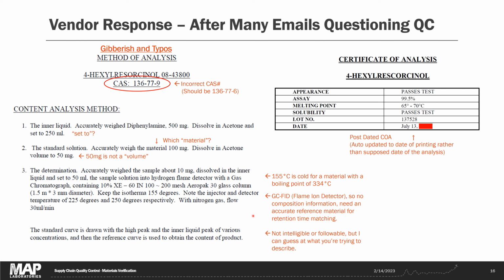One thing worth noting here is that the vendor claims to have used GC-FID, that's a flame ionization detector, rather than a mass spectrometer detector. The FID has really good detection limits and more even response to different types of molecules than the mass spectrometer does. But the downside of the FID is that it's just burning the sample as it comes out of the column and seeing how much material is there in that flame. It doesn't give you any composition information. It only gives you the retention time. So you really need a good reference so that you know for sure that you're matching the retention time to the actual compound you're looking for. And even then, things can potentially overlap.